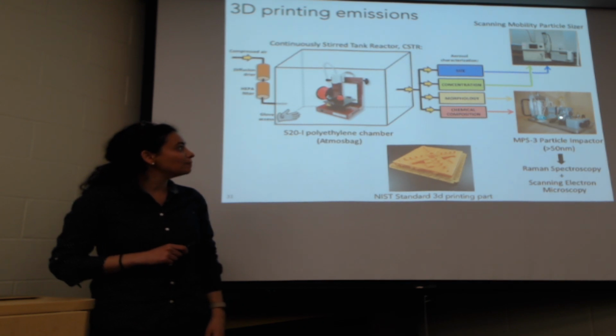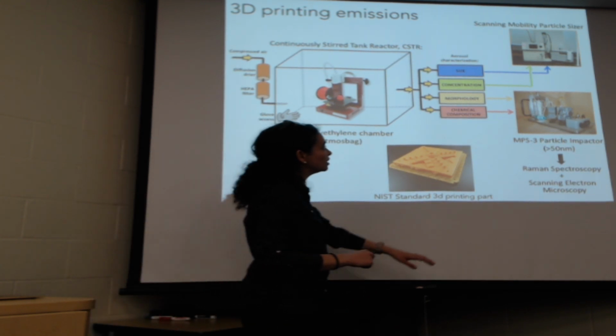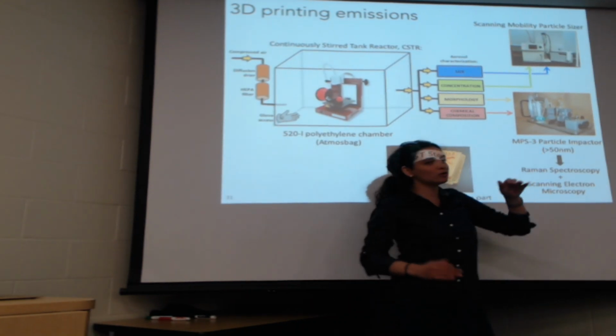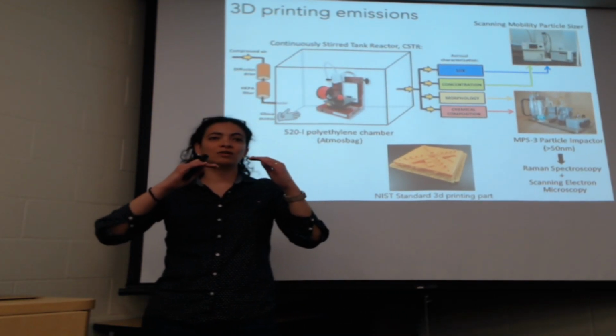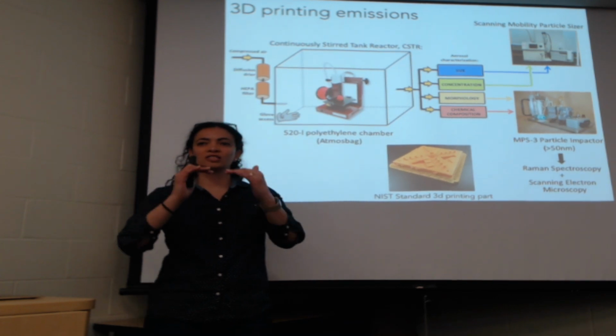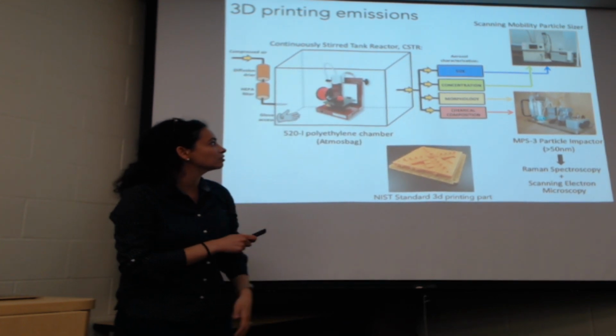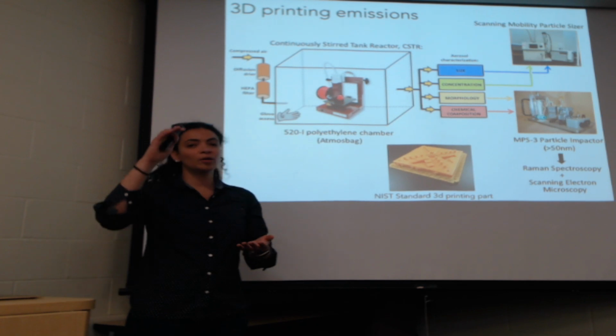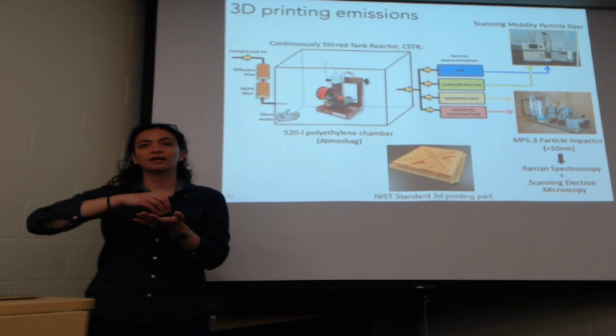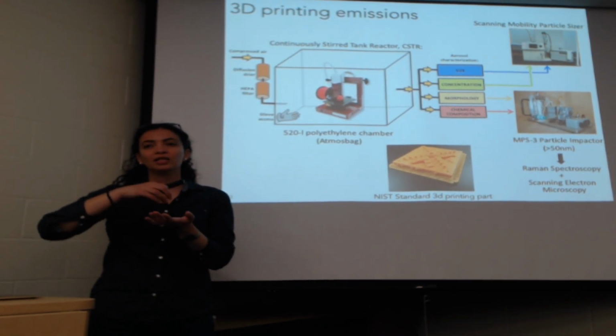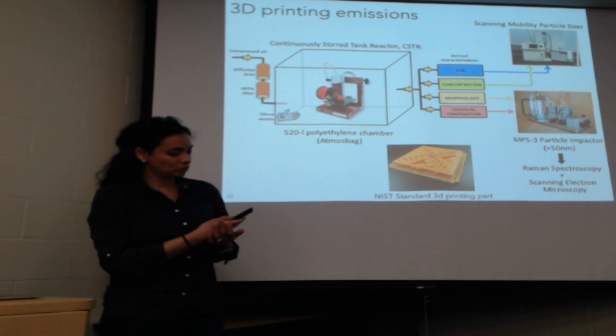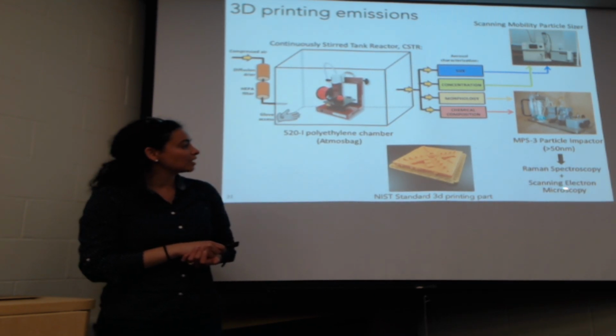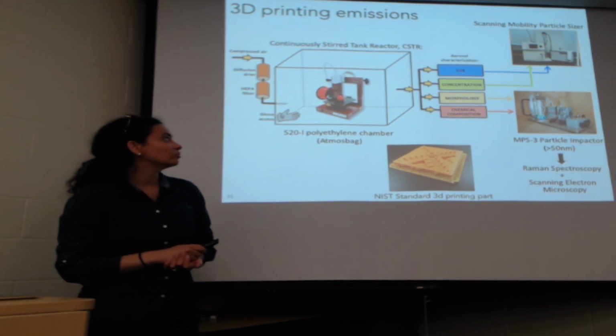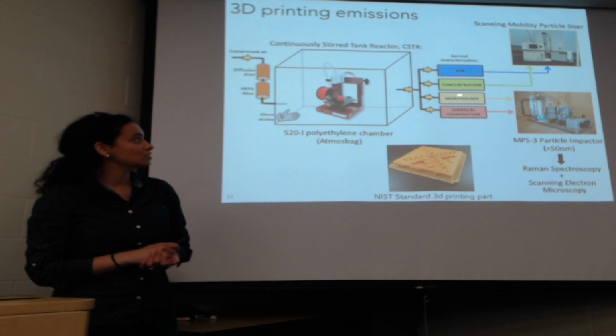And then we have this impactor, a tiny little instrument with 3 stages over here, where particles impact on a surface, and you can segregate them by size too. We had different stages, and we were looking at the smallest particles we could possibly impact there. The particles were impacted on a silicon wafer substrate, and then we took that silicon wafer to do some Raman spectroscopy analysis and scanning electron microscopy analysis. I'll talk to you a little bit about Raman later, so you get an idea of what that is. That gave us some information on morphology and chemical composition.